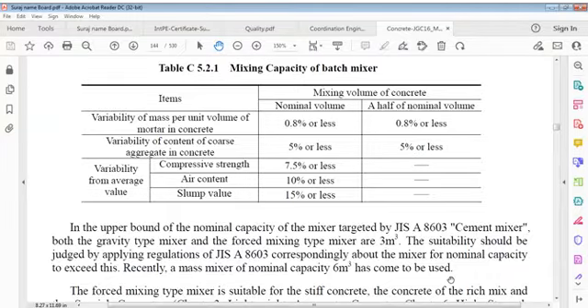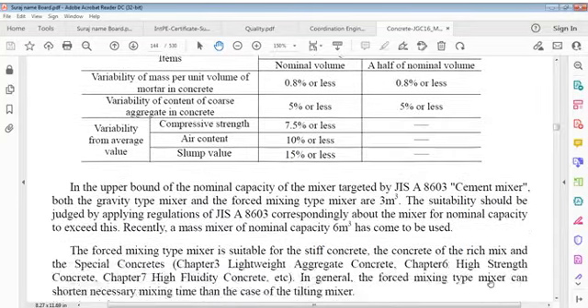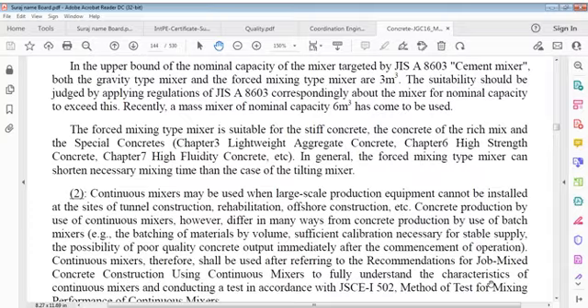Then variability of content of coarse aggregate in concrete is 5% or less in nominal volume. Then variability from average values: compressive strength is 7.5% or less, air content is 10% or less, slump value is 15% or less.